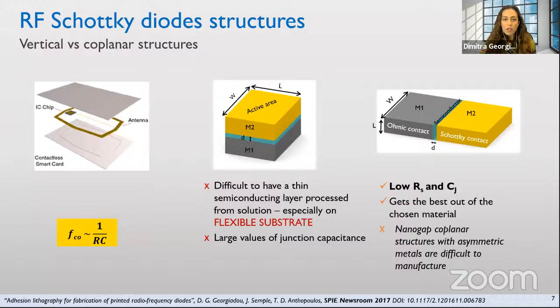If we now check how the standard Schottky diodes are being made, we see that this is based mainly on a vertical configuration where we have two metals and the active layer is sandwiched between those two layers. However, if we move to flexible electronics and use an active material which is processed from solution, then we have certain restrictions in terms of how thin we can make those films, because in very thin films, the homogeneity is not great, and we may have pinholes in the films as we deposit them.